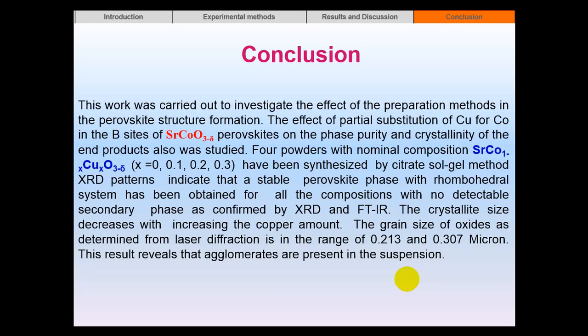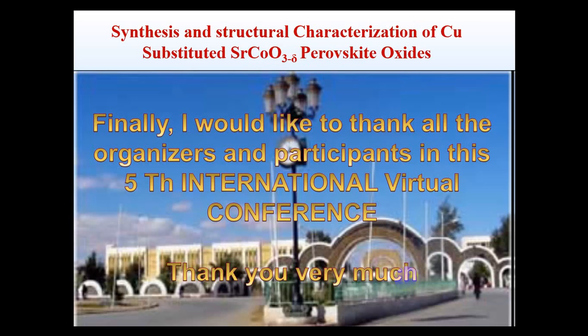The crystallite size decreases with increasing copper amount. The grain size of the oxides as determined from laser diffraction is in the range of 0.213 and 0.307 micron. This result reveals that agglomerates are present in the suspension.